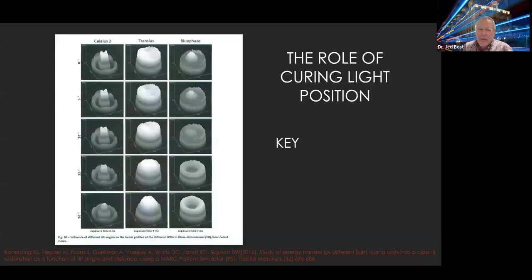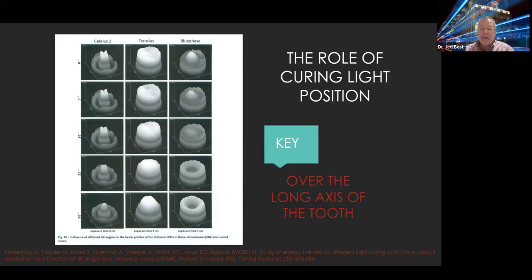Now, what happens if you're curing and you're not curing down the long axis of the tooth? Well, these are various diagrams of what the energy coming out of a light looks like depending upon the angle of deflection of the light. So on the top, there's no deflection. The light is going clearly through the long axis of the tooth. And on the bottom, there's a 20-degree deflection. And you can see very clearly that the cone changes. So take the blue phase as a perfect example. We go from a cone that actually has some sort of pyramid shape to a shape that's totally inverted. So if you're using this and you're not going down the long axis of the tooth, as an example, the center of the composite resin is not being cured nearly to the extent that the side of the composite is. You're not going to know it because the problem doesn't surface itself at the surface. It shows itself deeper into the penetration of the resin material.